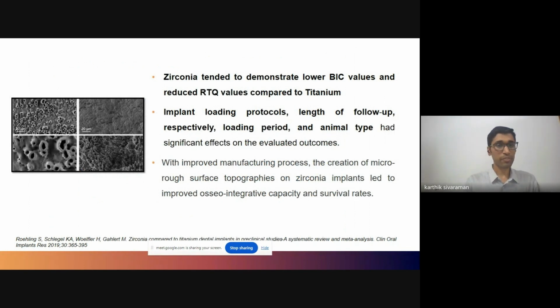So I'll just tell you about one more study here, and this was again done by Rowling et al. in 2019, whereby zirconia was compared to titanium dental implants in preclinical studies. It's again a systematic review and meta-analysis in 2019. So what did these authors conclude? They found that zirconia tended to demonstrate lower bone implant contact values and reduced removal torque values compared to titanium. However, they mentioned that there is a serious limitation to the observation they have given. There are various criteria which tend to affect the overall assessment in the form of implant loading protocol, the length of the follow-up, loading period, and the animal type.